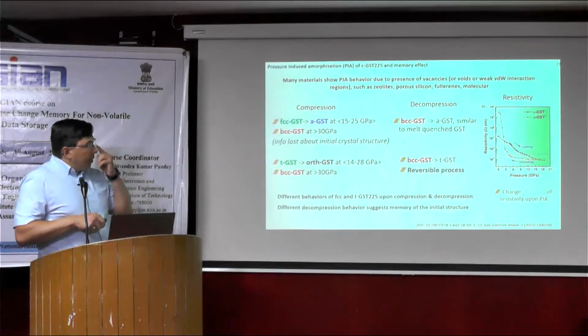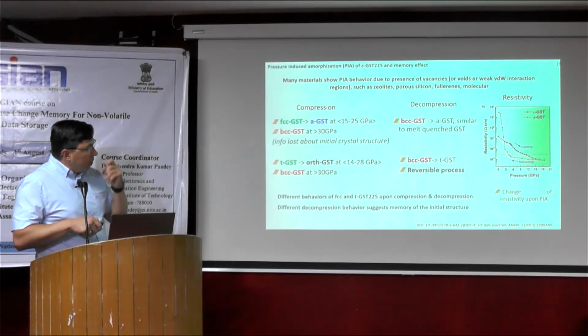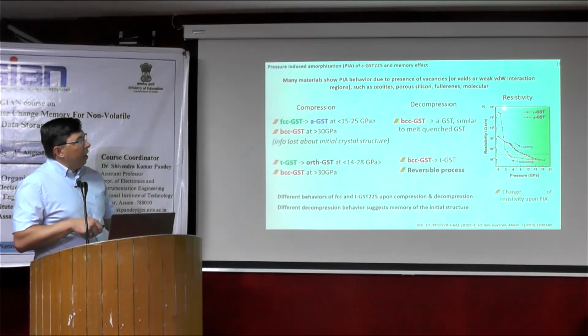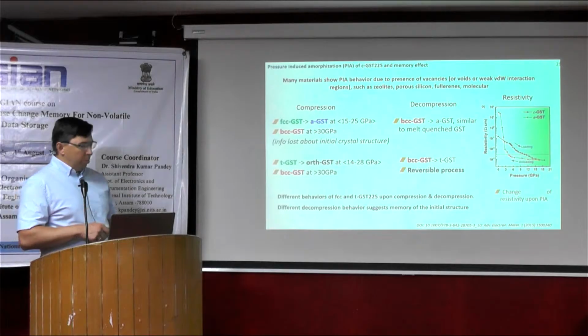Also, there is a change in the properties of the phases. If you compress the FCC GST, the resistivity changes on loading, and then on compression it goes up to a higher value, showing the formation of the amorphous phase.